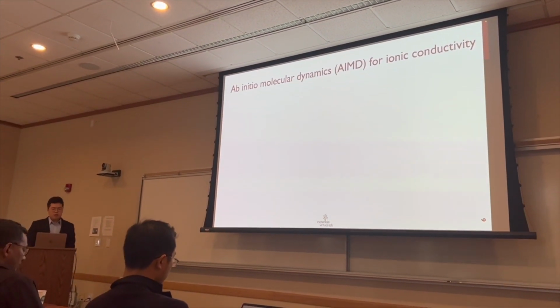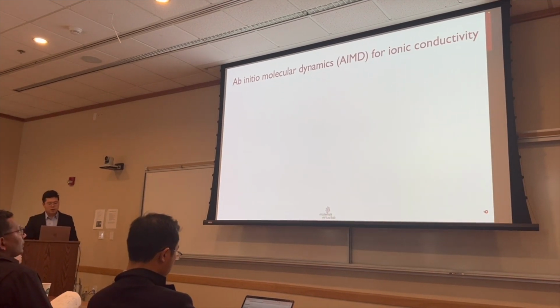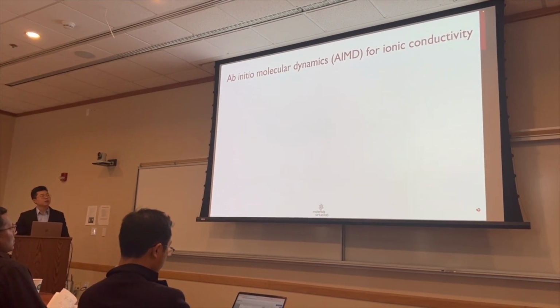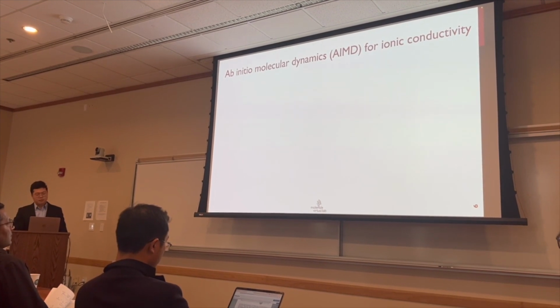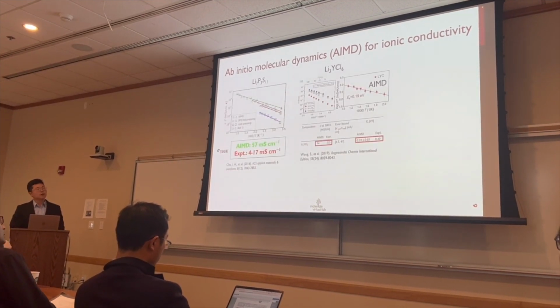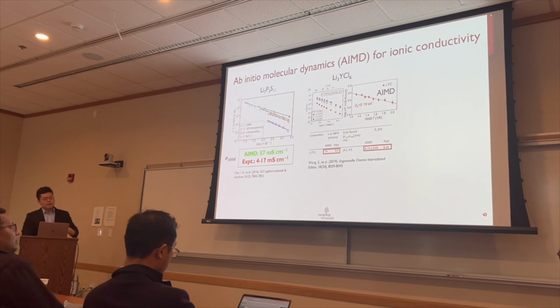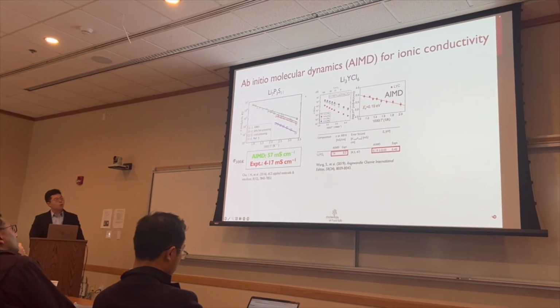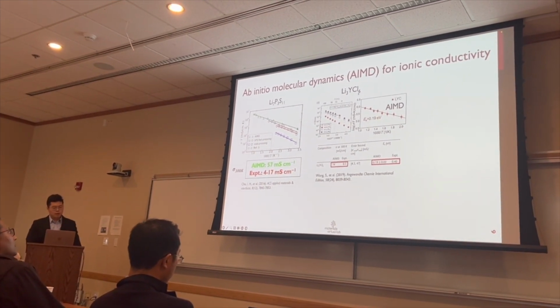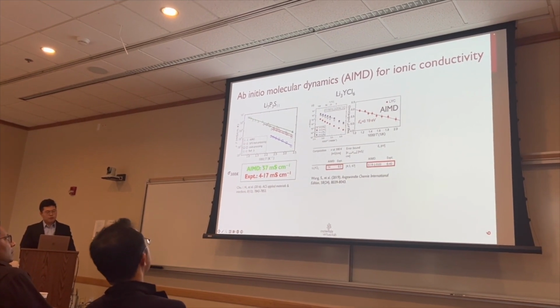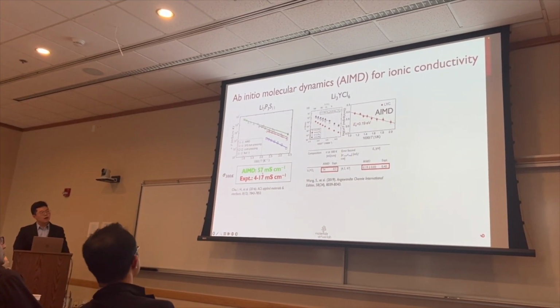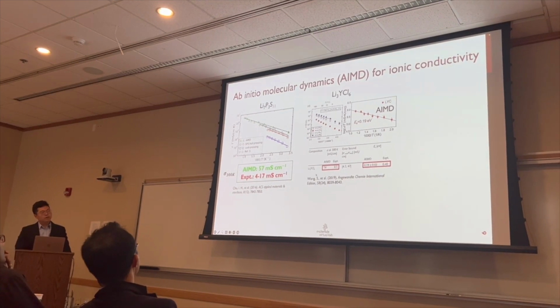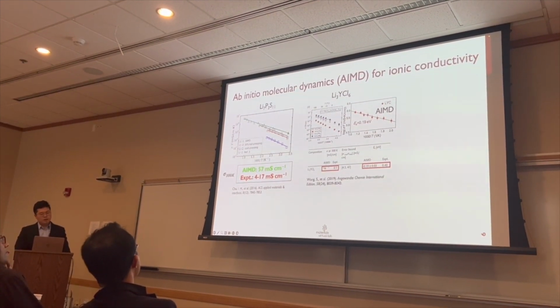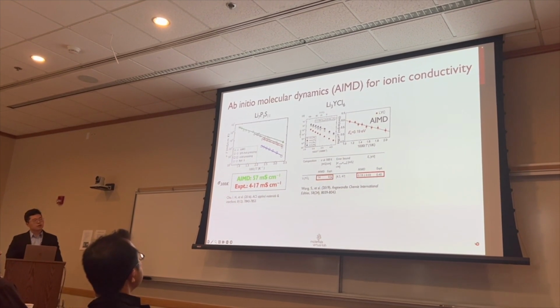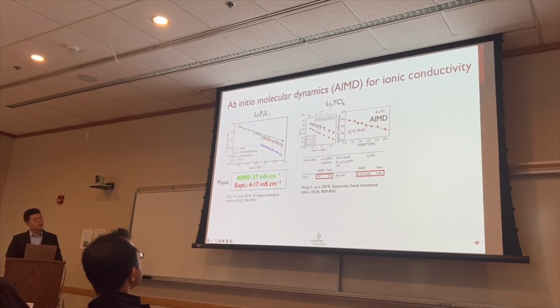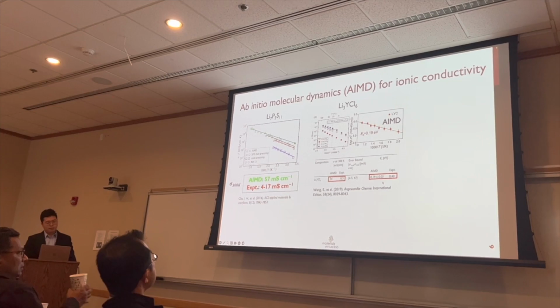However, ab initio simulation is known to have a challenge for reliable simulation of ionic conductivity at room temperature. Here I list two examples. The first one is Li7P3S11, and the second one is Li3YCl6. For both systems, you can see the AIMD simulated result is a few times higher, or even more than 10 times overestimated, compared to the experimentally measured room temperature ionic conductivity. And the activation energy is actually underestimated.